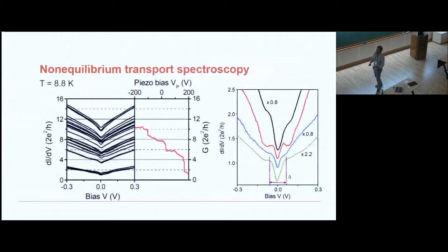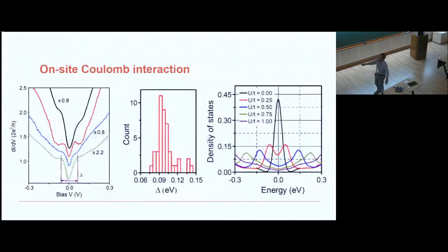Okay. There are very interesting properties. I'll go in 1 or 2 minutes. Essentially, this is a gapped structure. If you do a non-equilibrium transport spectroscopy, dI/dV, then you get a peak at the two sides, and there's a gap, which is very interesting because that seems to be saying that there's a strong interaction in the system. And Manish Jain and his student calculated that it translates to the on-site Hubbard interaction U of approximately 0.25, which is slightly smaller than other experiments. Other experiments say about 0.5, but it could be a strong screening that could limit the interaction.